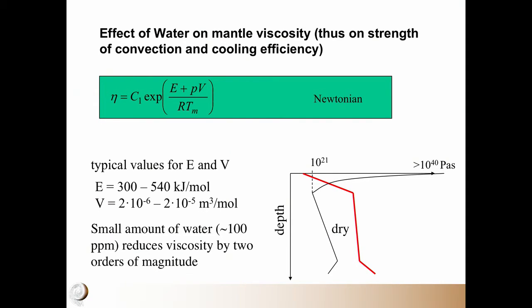Maybe I explain that first. This is the depth, and this is either viscosity or temperature. This is a typical temperature profile. You have a cold surface, you have a thermal boundary layer where you increase the temperature. In the interior, more or less a constant temperature which increases with the adiabat, and then you have a lower boundary layer here. The important thing is, at the surface with low temperature, you have extremely high viscosity. At these viscosities, nothing happens with the flow. It's really stiff, so there's no convection.